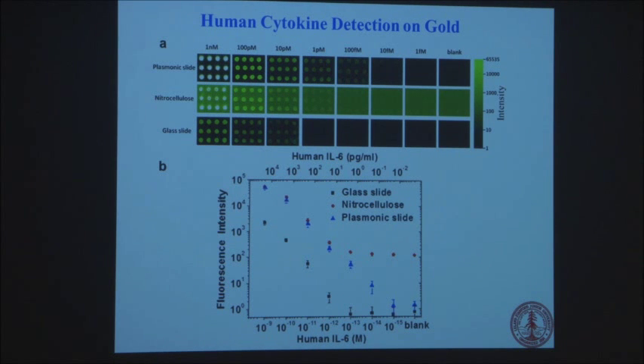Another example has to do with cytokines, and cytokines are molecules that often come up in the body if you have an inflammation of some sort, including cancer, which is a huge inflammation. So you can see that, again, on gold, we have a lot of signal, very low background, and on glass, the signal is 2 orders of magnitude lower, and sensitivity is lower. Nitrocellulose, the background is very high.